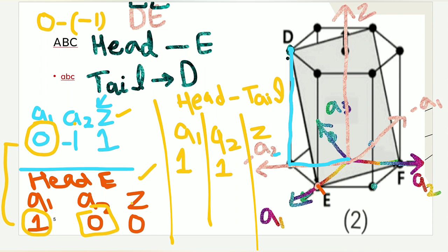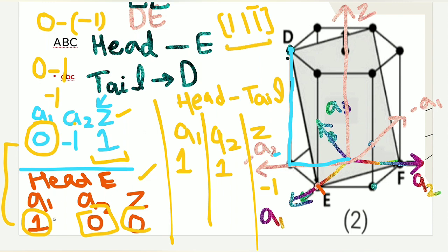And for Z, we have head coordinate 0 and tail coordinate -1. So head minus tail, 0 minus (-1) is equal to 1. Okay, it looks like that. So -1 is the result. And we got 1, 1, -1 as the Miller indices for the DE direction. So 1, 1 and -1, which is represented by putting a bar over the number, enclosed in square brackets. So these are the Miller indices of the DE direction, and now we'll calculate the Miller-Bravais indices